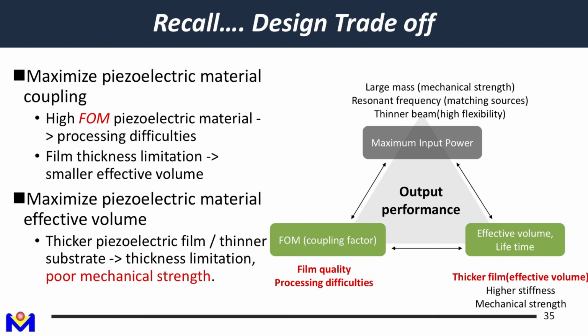For example, the CSD, the high performance PZT process based on the sol-gel process, can deposit very high performance PZT thin film. But the thickness limit is about 2 to 3 micron. Also the PLD, which I just mentioned, for single crystal PMN-PT thin film, the thickness is also limited by the process to about 2 micron. And again, you have to take the mechanical strength into consideration. If you have a thinner piezoelectric film, which is a ceramic, brittle material, and a thinner substrate, either silicon or stainless steel, it leads to poor mechanical strength, because even silicon has better mechanical strength than piezoelectric ceramic in general. So you will have, again, a design trade-off between these two factors.